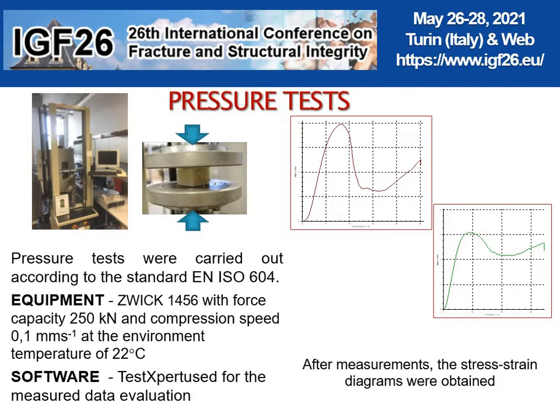Tests were performed at a relative humidity of 60%. Cross beam feed was 1 mm per minute, and all experimentally obtained results are presented as force-displacement diagrams. Here you can see two examples of performed pressure tests on two samples.